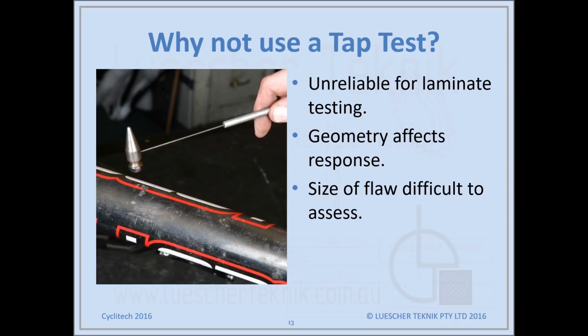But a bike frame is a much different scenario, and what we find is that it's very difficult to accurately size and assess a flaw or damage. If you have visible damage, it may tap, and that's about what you can use it for, but then you can usually see the damage visually anyway, so it just confirms that. It certainly hasn't got the sensitivity to find a delamination within the laminate and accurately size that.